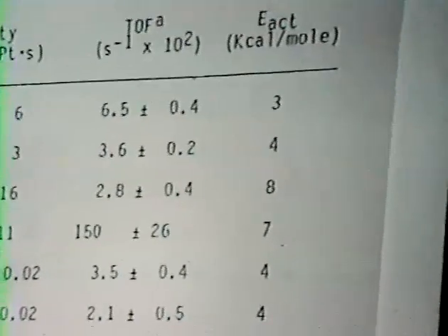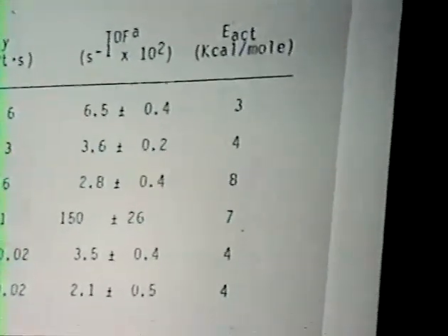I want to stress at this point that these low values do not imply diffusion limitations. We tested for those, and in addition, if you go to the literature and you look at activation energies for the hydrogenation of olefins, these values range in the order of 4 to 6 kilocalories per mole. So they're well within the values expected for hydrogenation of carbon-carbon double bonds.